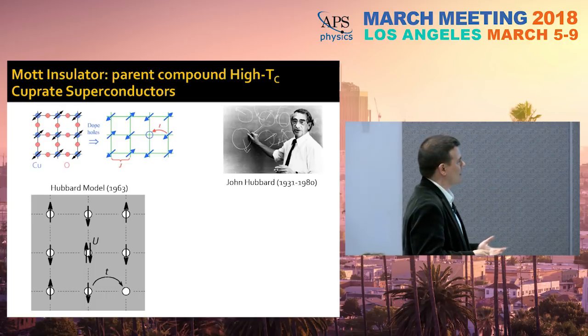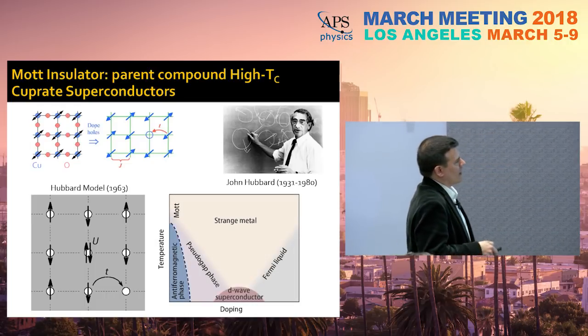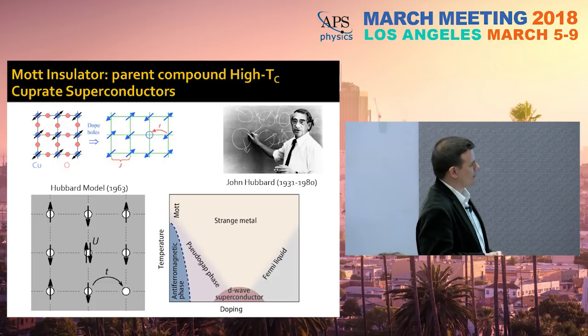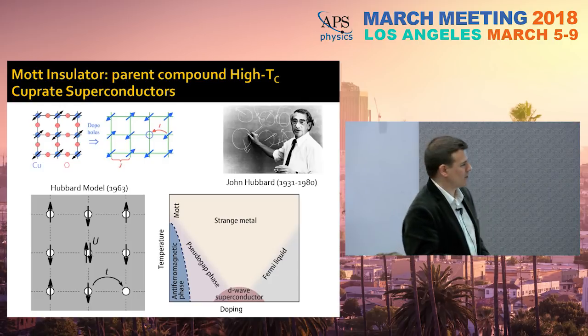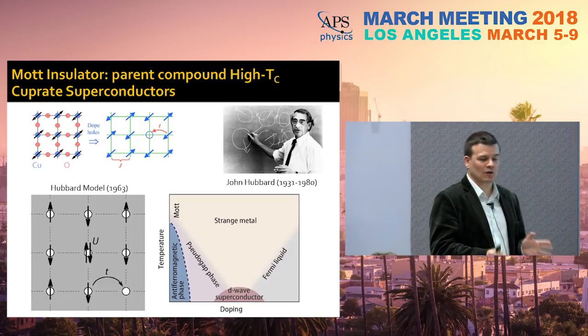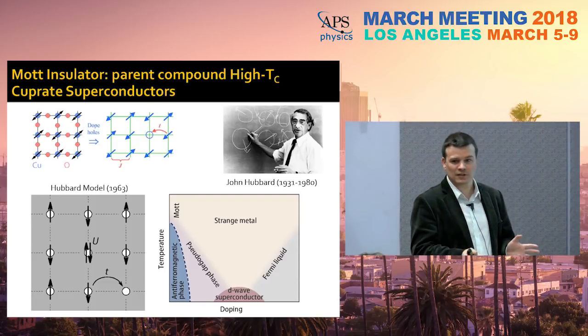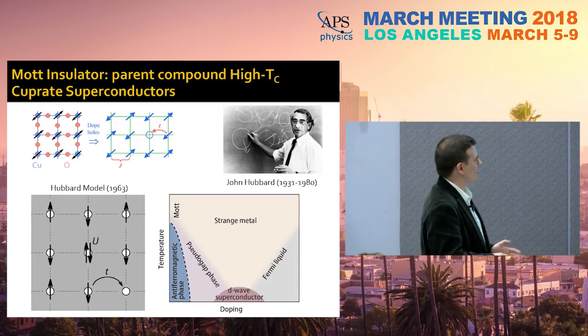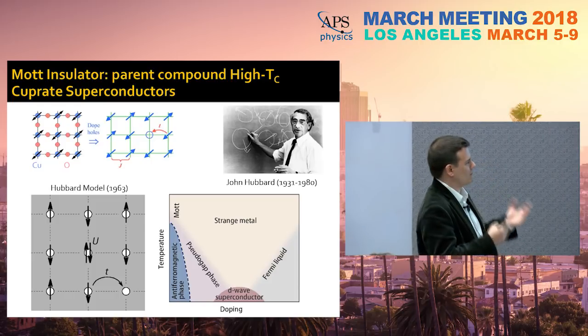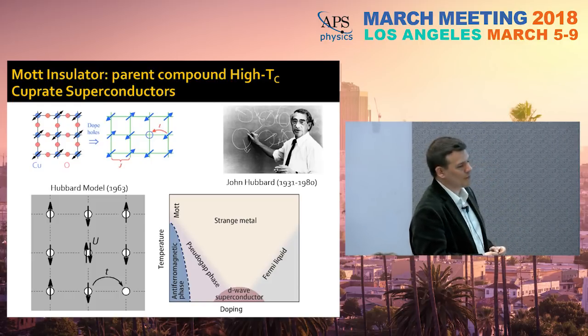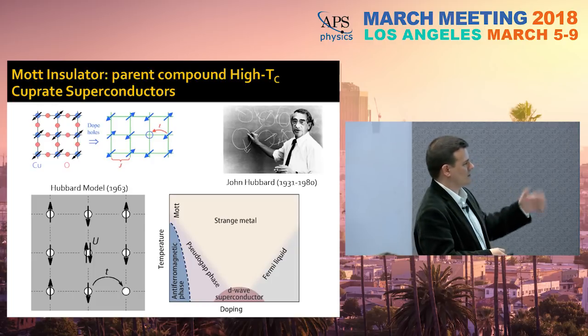And it turns out that a superconducting dome appears upon doping sufficiently, and all other kinds of strange physics appear in this situation. This is something which is typically modeled with the so-called Hubbard model. It's a model that we cannot solve analytically, perfectly, theoretically. And as a result, for three decades since cuprates were discovered, there's been a lot of work, and this model is also used for many other correlated materials.